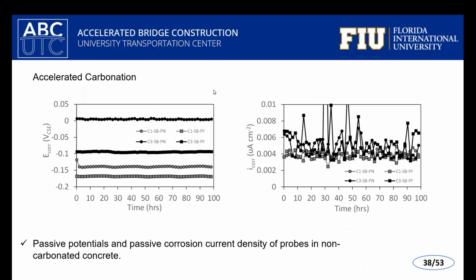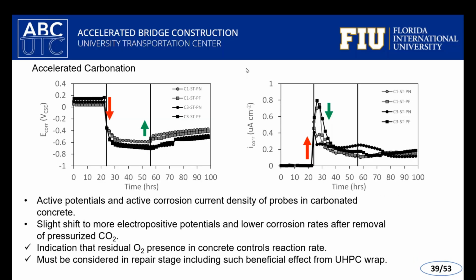And then we measured the half-cell potential and the corrosion rate beforehand, again, before the carbonation process, just to verify that the steel indeed is passive. So the corrosion potentials are fairly electropositive, more positive than about minus 150 millivolts versus the copper sulfate electrode, for those of you keeping track. And the corrosion current density, again, is very, very low, shown in the graph on the right. But then what happened when we introduced that pressure vessel? That shows the shift when carbonation occurred.